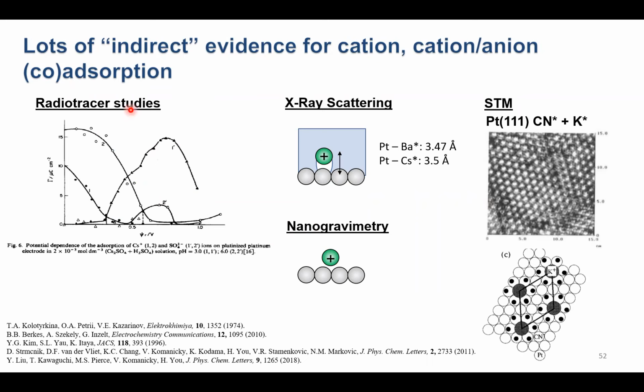Just very briefly, there are a lot of radiotracer studies from the 70s and 80s, mostly from researchers in the Soviet Union, where they used radioactive isotopes of alkali metal cations to directly measure their coverage on the surface, independent of the voltammetry. Here we're showing coverage versus potential of a cesium cation at pH 3 on, I believe, a platinum electrode. We can directly measure this coverage and see that it increases with decreasing potential. This could just be cations in the double layer.